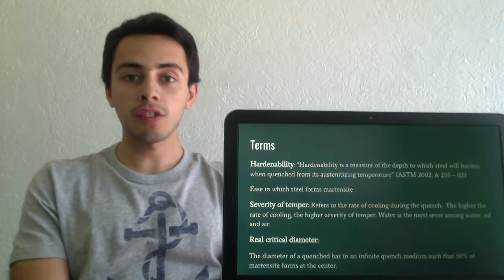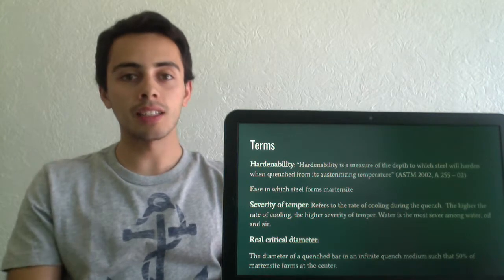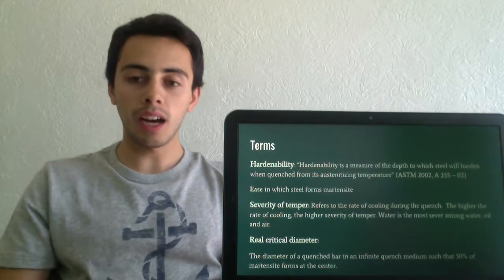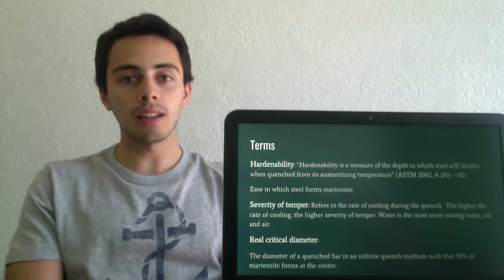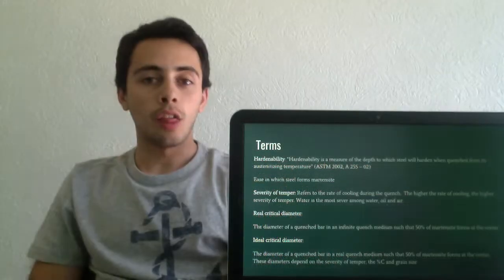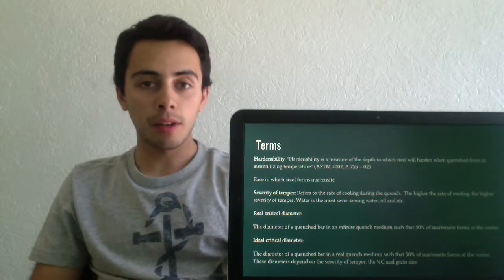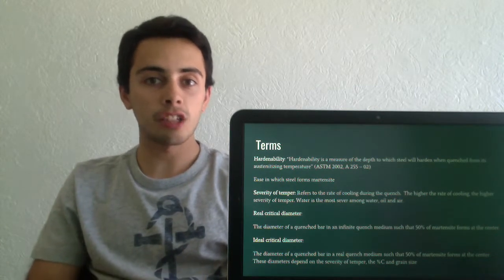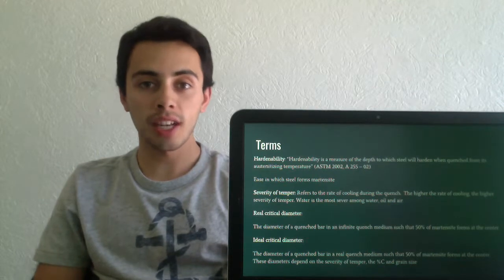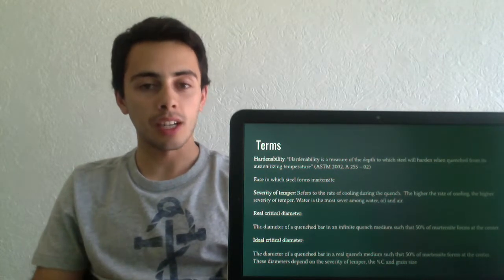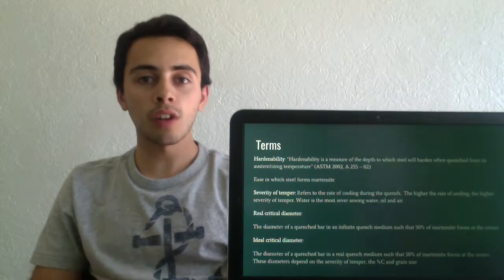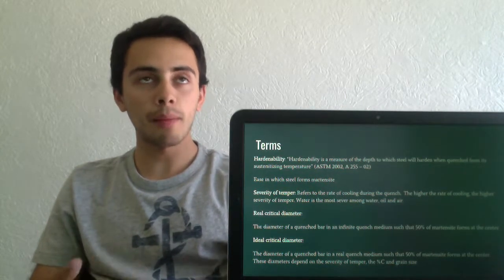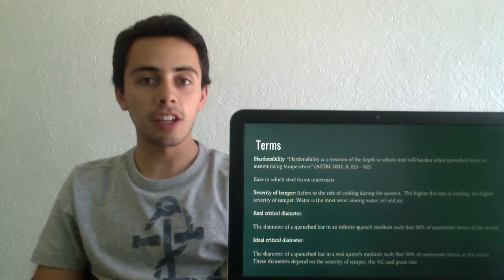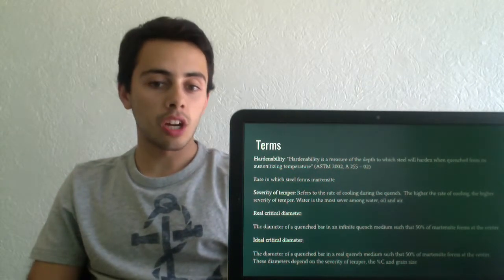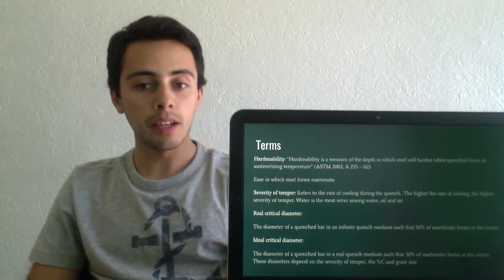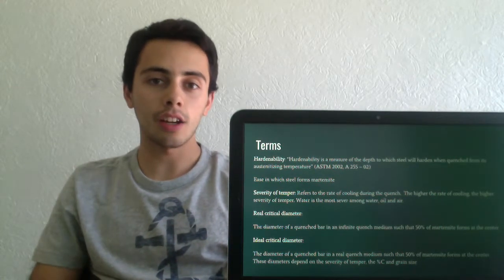In addition, the severity of quench refers to the cooling rate, and it is how high this cooling rate is. A high cooling rate means it is a severe quench. The real critical diameter refers to the diameter of a bar that has been quenched in an infinite quench medium, and at the center 50% of the material has become martensite. In contrast, the ideal critical diameter is this same parameter, but in a real quench medium. This diameter depends on the severity of the quench medium, the percentage of carbon, and the grain size.